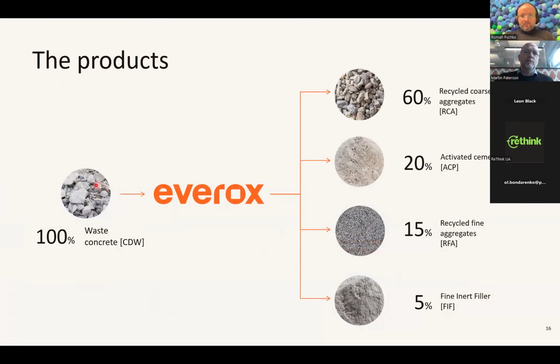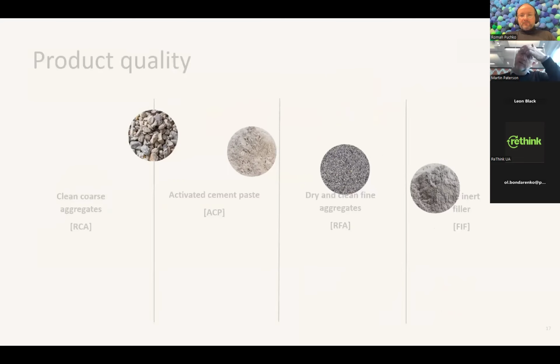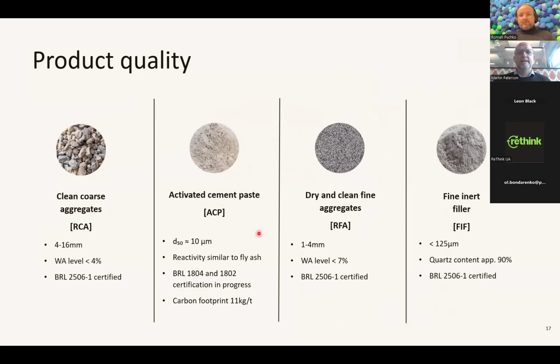So in summary, in a nutshell, we put waste concrete into our process without any waste, without any byproducts. We get, depending on the nature of the concrete, but this is a good rule of thumb, 60% RCA, 15% recycled fine aggregates, then a small amount of fine inert filler, and roughly 20% of the activated cement paste. And looking at the quality of that material, what we see now on a constant basis is that the aggregates we get out of it are very clean and can be used to a high degree in concrete as replacement of primary products. So the coarse aggregates have a water absorption level below 4%, the fine aggregates below 7 or even below 6%, as I said.